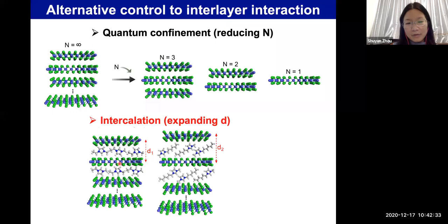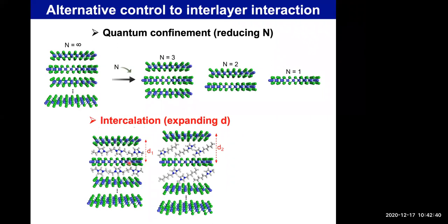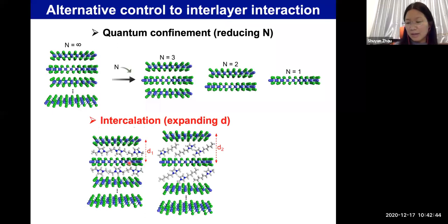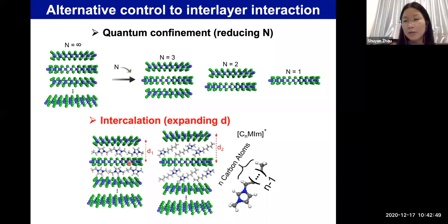For example, these layered materials have a large van der Waals gap between the layers. And if we can use different sizes of ions to increase the interlayer spacing, then we can reduce the interlayer coupling, and probably we can attain properties similar to the monolayer flake. Now, the ions that we choose to intercalate are these cations from the ionic liquids.